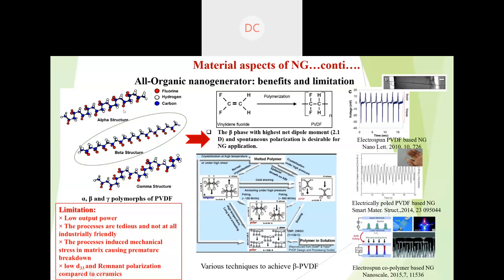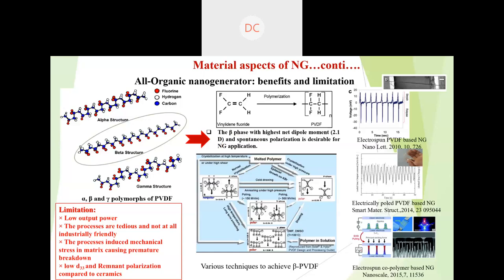So to make the phase transformation from alpha to beta, a lot of techniques have been adopted by previous researchers, including crystallization at high temperature, applying high pressure, cold drawing, annealing or epitaxial growth. But all these processes are very tedious and not at all industrial friendly for large scale production. These processes also incorporate some surface defects in the material, and thus the mechanical property of this material is hampered, which brings premature breakdown strength of this material.